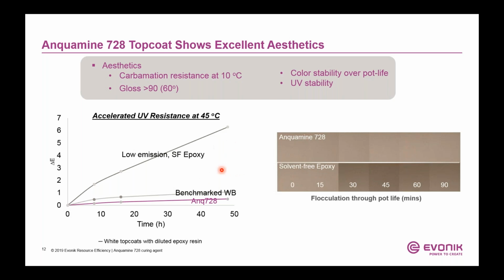These are all known to exhibit excellent UV resistance. From this test, you can see that Anquamine 728 outperforms the solvent-free system, and it has slightly better UV resistance than benchmark waterborne epoxies. So it definitely has very good UV stability. Also, it does not show any pigment flocculation within pot life. Within 90 minutes, we compare Anquamine 728 with a solvent-free system. The solvent-free system definitely shows some color drift within 90 minutes, and the Anquamine 728 top coat shows very consistent color.